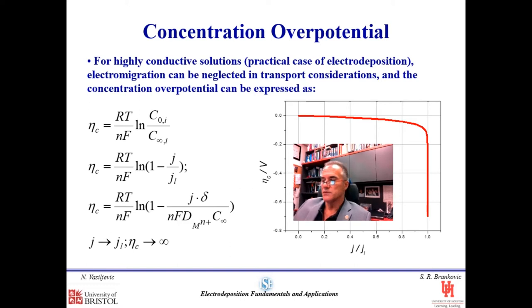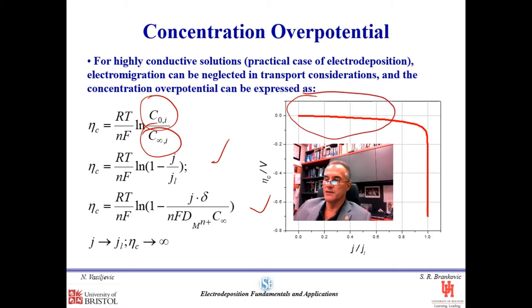Because of the transport limitations, we also have an important phenomenon, which is related to concentration overpotential. Concentration overpotential is a function of the concentrations of the ions at the interface and bulk concentrations. In particular, it's a function of the logarithm of their ratio. And more importantly, you should appreciate that there are different forms of this expression, whether we express the concentration at the interface in terms of the current density that flows through the interface. You can have a different definition. One important thing to appreciate is that the contribution of concentration polarization is very small for any ratio smaller than 0.9. It's truly negligible.